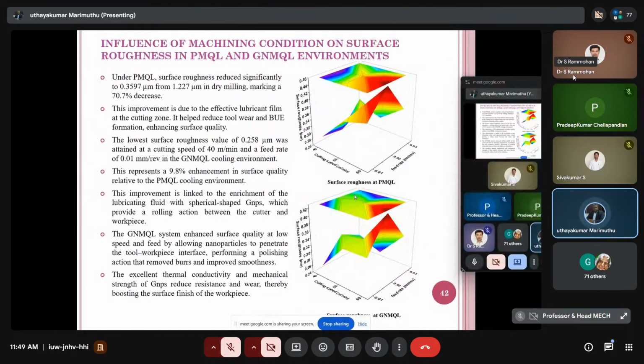So here you can see the surface roughness. Another parameter is surface roughness. Earlier it was the cutting temperature, now surface roughness in the same environment, right? So under PMQL, surface roughness reduced significantly to 0.3597 microns from 1.227 microns in dry milling. Right, 70% decreased. So a smooth surface we have attained by using this one.